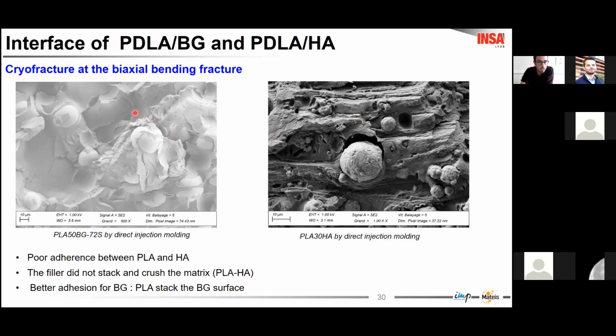And we can see here, in the case of bioglass, that there's part of PLA stuck on the surface of the bioglass, and maybe that's showing better adherence between the matrix and the filler.